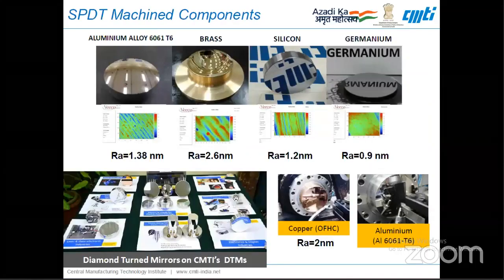Now we'll look into the component accuracies we achieve using the single point diamond turning process. On different materials, as I told you, it can machine aluminum, copper, brass and others. Here you can get a surface finish down to 1 nanometer and 2 nanometers in aluminum, brass, copper and other materials. And we can even machine silicon and germanium, which are crystalline IR materials. When you try to machine these materials by other processes, they tend to have brittle fracture on the surface.